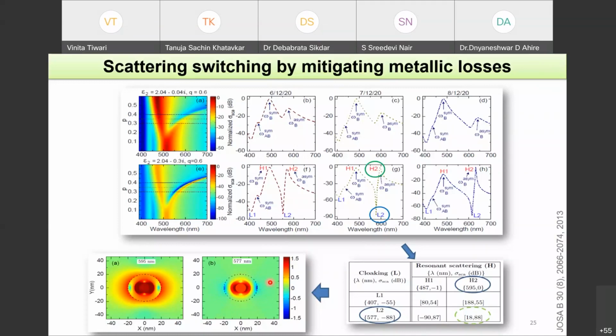So this nanoparticle is basically in a cloaked state or an off state. It has concentrated all its electric field inside the dielectric layer. So this is the high contrast regime. So you can use this nanoparticle at 595 nanometer as an on switch, and this you can use as an off switch. So this is how you can design very high speed scattering switching based on nanoparticles.